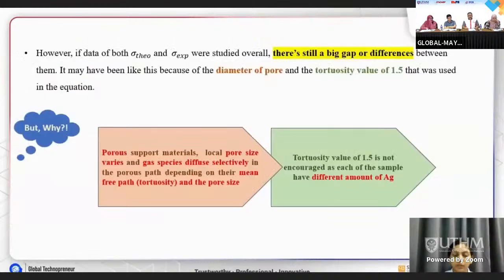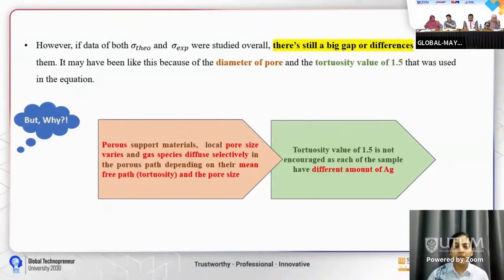From the previous data, we can deduce that both the theoretical and experimental conductivity are high at 600 degrees Celsius. However, there's still a big gap between them. This is because of the diameter of the pore and the tortuosity value of 1.5. The pore size varies depending on the mean free path, which eventually depends on the tortuosity values. And the tortuosity value in this research has been fixed at about 1.5. This is not encouraged as all of the samples have different amounts of Ag.